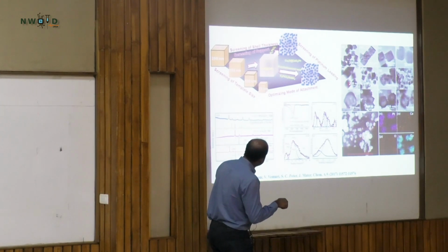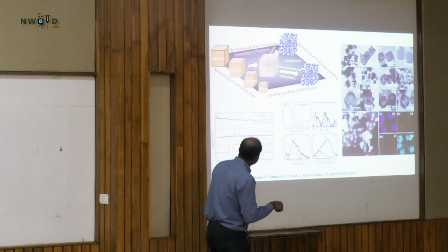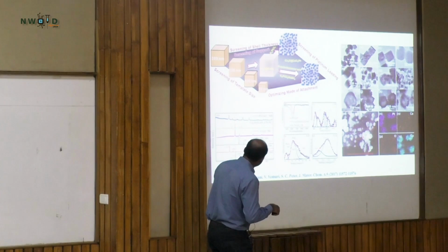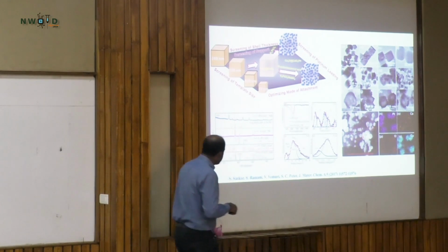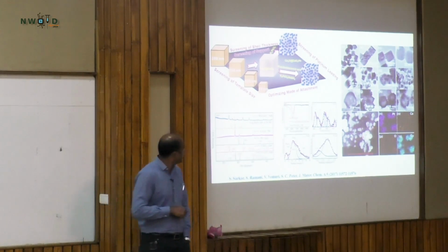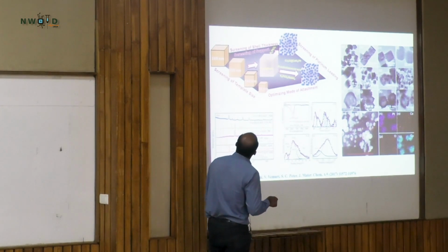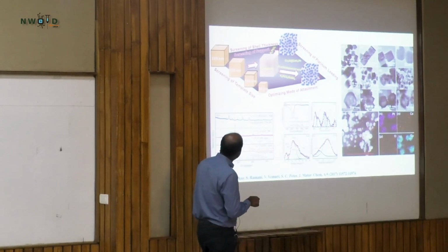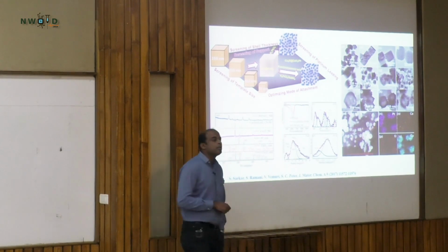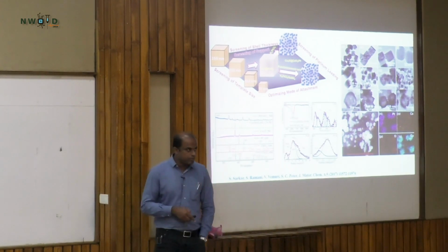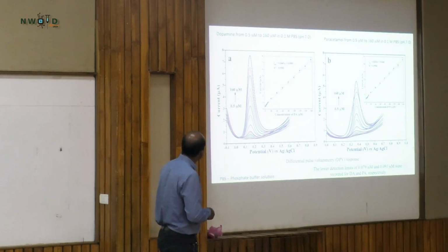It's not the shape actually, the surface is changed, and it's characterized by all the elements at the surface of this one. This is also characterized by XRD, EXAFS and XPS, by various techniques, and we confirm that the platinum is uniformly reduced at the surface of the nanoboxes. So we can control the concentration of the platinum depending on whatever input we are giving.